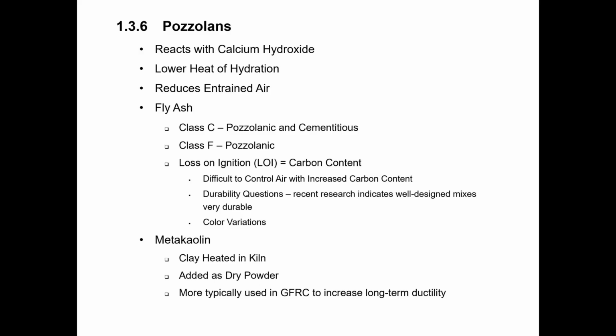There's also been some research that indicated that higher carbon contents decreased the durability of the concrete. But as more and more research has been done in this area, the consensus of the research seems to be that with a well-designed mix using a high carbon content fly ash, you can still get a very durable mix. So that's good, especially in this day of carbon capture and trying to encapsulate as much carbon as we can into the concrete to reduce the carbon footprint of the cement manufacturing process.